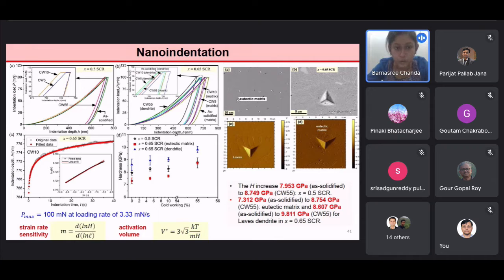And figure B shows the load versus depth curve for the matrix as well as for the dendrites, for the as-solidified specimen, for the 5% deformed specimen, for the 10% deformed specimen, and for the 55% deformed specimen. Further, to evaluate the strain rate and strain rate sensitivity, we have plotted the indentation depth versus indentation time, and from there we have plotted and fitted the ln H versus ln strain rate. From there we have evaluated the strain rate sensitivity.